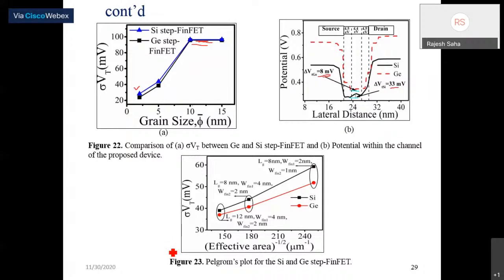Okay. So next we have the Pelgrom plot. This is the name of the scientist. The plot is between the variation in the threshold voltage versus 1 by square root of effective area. As you can see, the threshold voltage variation is less for the germanium device compared to the silicon. Red color indicates the germanium. Similarly, as 1 by square root of effective area increases, the variation in the threshold voltage increases, because the number of grains within the gate area is increasing.